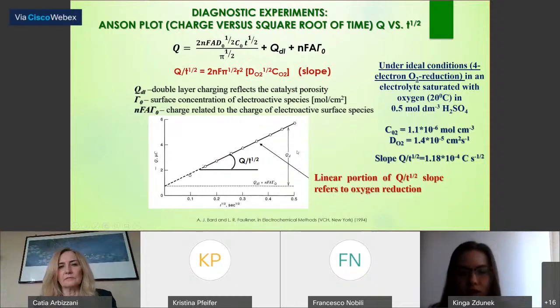This slide illustrates diagnostic experiments. We can see a quadratic equation. The first part is diffusion, but the second, Qdl, is double layer charging, which reflects the catalyst porosity. And the third is the charge related to the electroactive surface species. The second and the third are not the diffusion part. On the right side, you can see concentration, diffusion coefficient, and slope for four-electron oxygen reduction in acid medium. For the linear portion, we calculated the slope, and it is ideal.